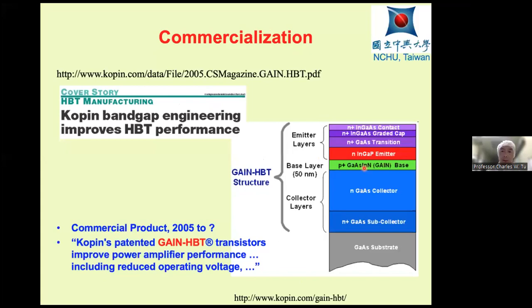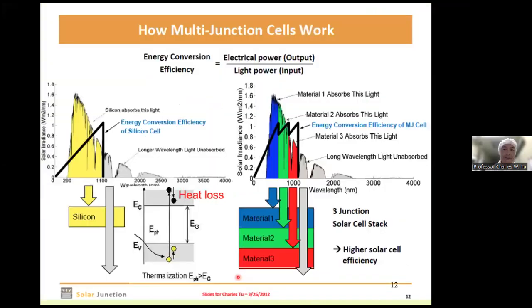Now the other application of this band gap reduction is in solar cells. Here I show the solar spectrum as a function of wavelength, and here I have a silicon solar cell, and 1100 nanometers, so that's about the silicon band gap. And you see the conversion efficiency is high near the band gap, but decreases when the wavelength is shorter. And this is because of the heat loss.